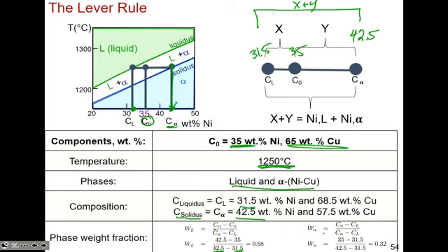The amount of liquid that exists right at this temperature is this, Y, 42.5 minus your composition, which is 35 right there. Then you could say the same thing: how much is solid? How much is alpha? Well, that's C naught minus CL, so 35 minus 31.5 over the same distance, because it's a fraction, and that gets you 0.32.